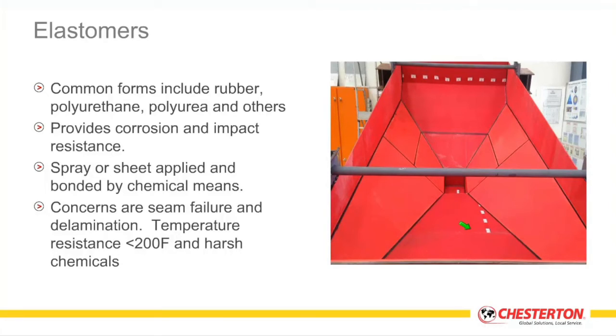Polyureas and polyurethanes are liquid applied systems. These can be spray applied, and these also will provide you slightly better corrosion resistance than many of your rubber-based systems, and they can be applied to irregular shapes as well. Concerns of your rubber-based sheet applied materials is seam failure. The seam often is the leak path. That's typically where permeation or abrasive wear will occur